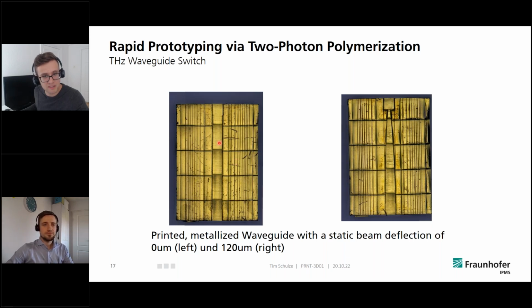But maybe you can also see that it's not perfectly smooth here. I mean, it's very smooth, but not perfectly. And when I applied gold on that, I was able to measure a surface roughness of about 0.4 micrometers. There are different measurements for surface roughness. So I'm considering the Ra value here. So the Ra value here was 0.4 micrometers. And this is what we attained here.